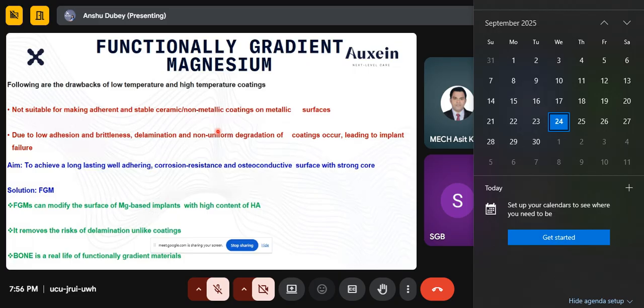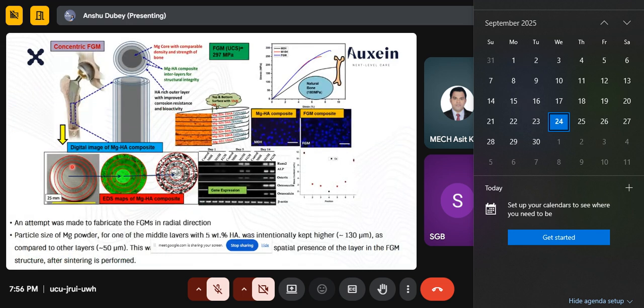So to eliminate the drawbacks of coatings, we developed a system which has a core of pure magnesium with increasing layers of hydroxyapatite. If you see, this initial core is magnesium with increasing layers of hydroxyapatite. In the EDS images, the green color demonstrates the magnesium, and the red color demonstrates the hydroxyapatite. So the red color increases towards the end. So we can say we successfully developed the concentric functional gradient material system for magnesium through